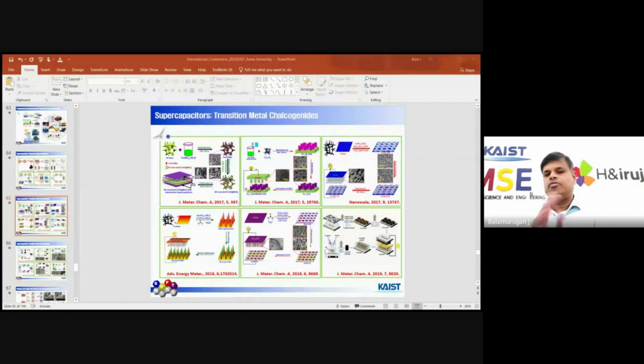Metal sulfide means a very smooth area, but in metal selenide, because selenium is bigger in size, the porosity will be enhanced. From the porosity, maybe we can get higher energy storage performance compared to the sulfide based material. Therefore, we have moved from sulfide to selenide.